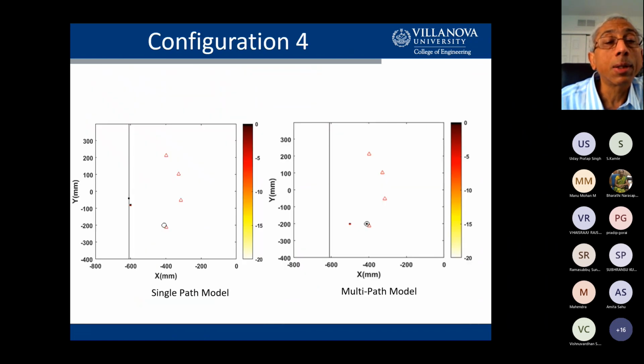Here's a case where I've got just one defect in my plate. It is situated at this open circle. Again, this is experimental results. These triangles, as before, are the 4 transducers that I have, and this represents an edge of a plate. And if I use just one path, the direct path, to try to identify where the defect is for this particular situation, the sparse reconstruction model says, well, the defect is over here, right at the edge of the plate, and it's nowhere near where the actual defect is. So the single path method just fails.